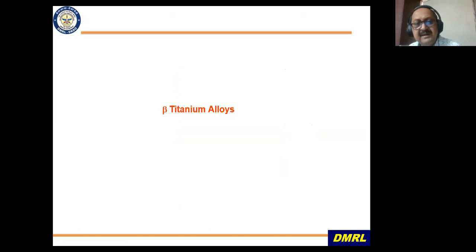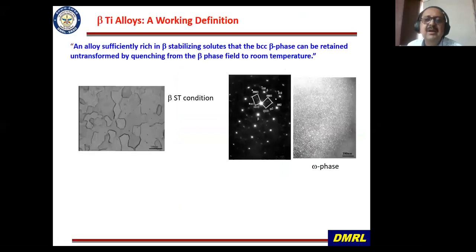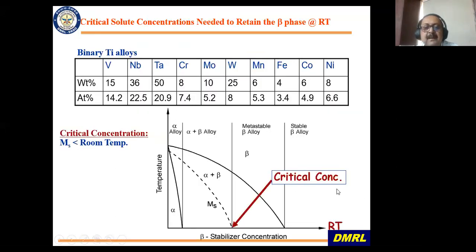Near alpha titanium alloys, now go on to beta alloys. Beta alloys, as I told you, have a much higher amount of beta stabilizers, and you can retain the single phase beta by quenching or faster cooling, and you also get very fine precipitation of omega phases. Most of the beta alloys, that is what you have to be careful with.